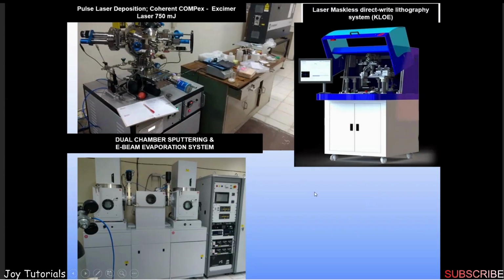So here are a few of the instruments which I have had in JNU. This is a pulsed laser deposition system for single crystalline epitaxial film growth of some magnetic insulators as well as magnetic metals. Of the magnetic insulators, yttrium iron garnet is the best insulator because it has a very narrow line width. If one wants to design a very narrow band filter, one has to go for this yttrium iron garnet structure. If one wants to go for a higher frequency, one has to go for iron, iron cobalt, or some kind of transition metal structure.